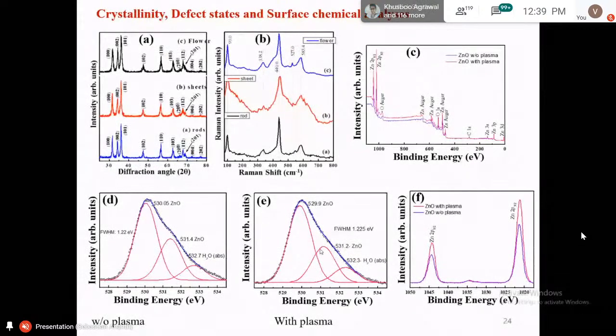This is the oxygen 1s spectra. So there are three kinds of oxygen incorporated with the prepared material. The first one is oxygen linked with zinc, that is 529.9 with this one. The second oxygen is related to the interstitial site, that is the lattice oxygen. And then the third is the oxygen absorbed due to the moisture from the atmosphere. It contains a small amount of moisture.